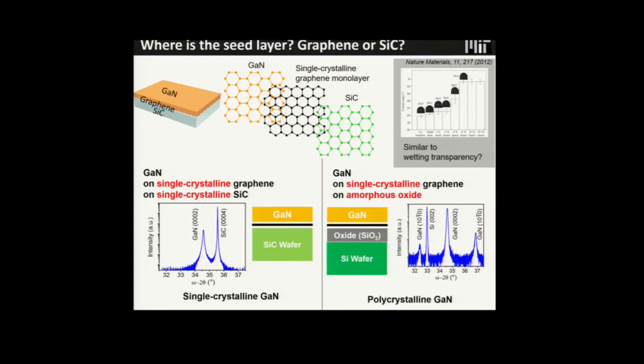Okay, when we make a single crystalline epitaxial graphene on silicon carbide, the structure is as follows. We have silicon carbide, we have a single crystalline graphene, then we have gallium nitride. But then the silicon carbide lattice is also hexagonal. So my assumption was right. Is this right? In the Nature Communications paper, I strongly said graphene is a seed layer, so that's why I grew single crystalline gallium nitride at wafer scale. But something was stuck in my heart. Maybe silicon carbide could be a seed layer because graphene is really thin, just a monolayer.